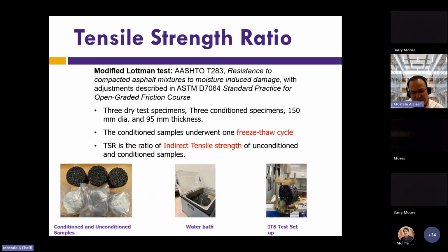The tensile strength ratio or the modified Lottman test consists of testing 3 specimens conditioned and 3 unconditioned. And then you measure the indirect tensile strength of the unconditioned and the conditioned. And the ratio of strength between the two gives you an indication of the moisture damage resistance of the mix. So for OGFC, NCHRP 155 recommended a TSR of 0.7. In ASTM, they recommend a TSR of 0.8. The state here in Louisiana doesn't use the TSR for OGFC, it uses the boiling test. But again, this test that I'm showing here is more scientific, and that's why we use it in our assessment. And we aim to achieve a TSR of 0.8 for our mix.